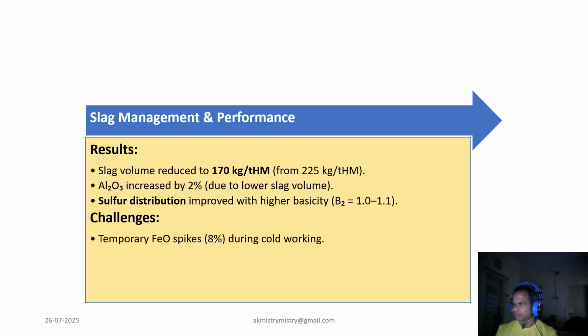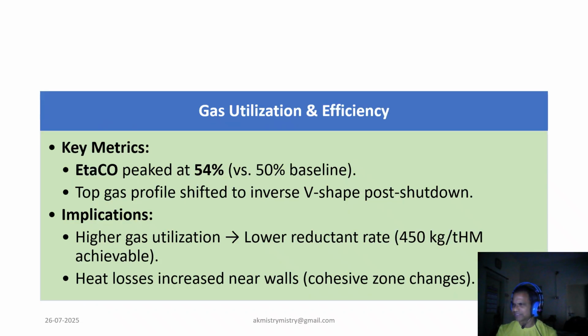Now coming to the most important aspect of efficiency, that is gas efficiency. Efficiency saw a notable boost, hitting around 54%, well above our baseline of 50%. So we can say that during this use, utilization has gone up by 4%, and this gives us a lot of benefit in terms of fuel saving. It is also seen that post shutdown, the top gas profile shifted to an inverse V shape, which came with a trade-off like increased wall heat losses due to changes in the cohesive zone due to the higher pellet use.